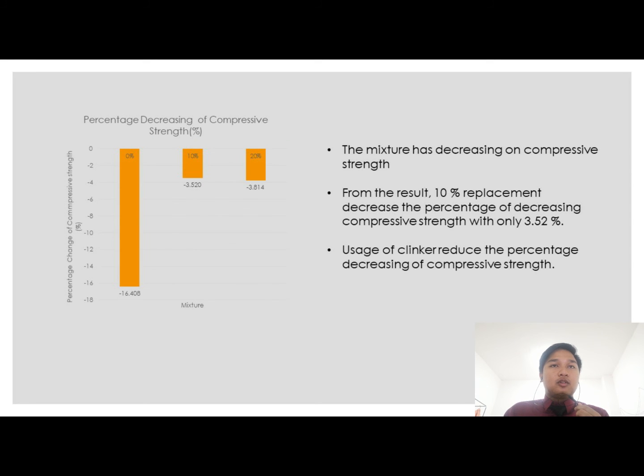Variation on percentage decrease of compressive strength. All the mixtures have decreasing compressive strength. From the result, 10% replacement has the lowest percentage decrease of compressive strength with only 3.52%, compared to the normal concrete, which recorded a 16.408% decrease of compressive strength. I can conclude the usage of clinker reduces the percentage decrease of the compressive strength.